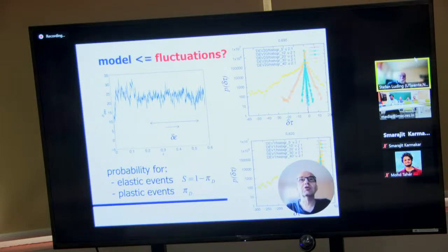Now, if you do the statistics a little bit more detailed, and better statistics, then you get the probability, and you see the yellow distribution. It's not centered around zero, it's slightly positive, that's the elastic division, and it's plastic on the negative side, and it's highly asymmetric. So the probability for elastic events is exponentially decreasing, so that's normal statistics. On the left-hand side, you have the possibility for rare events. So we have low probability for big stress drops. Okay, and that is special.